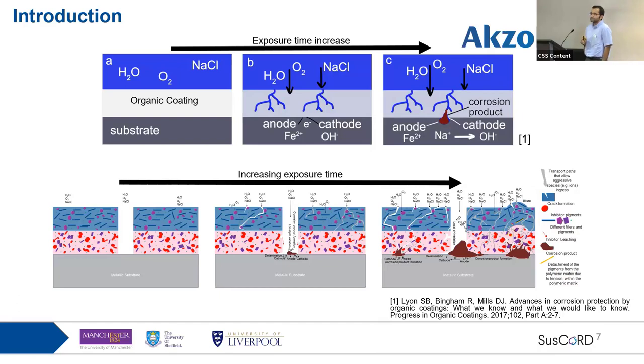But organic coatings are not a simple polymeric binder and curing agents, as it is mentioned by Simon. Actually, there are a lot of different active inhibitors, pigments, and additives added to the organic coatings. So it is important to understand how these different pigments affect the formation of these percolating networks and these heterogeneities within the coating and how they eventually result in the failure.